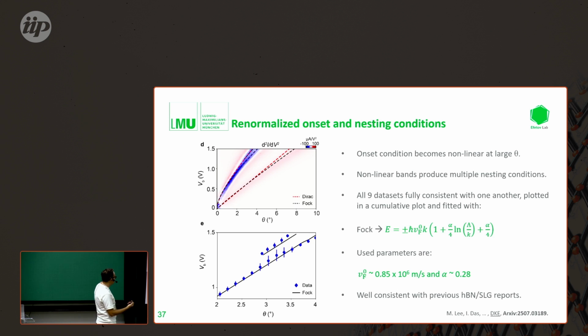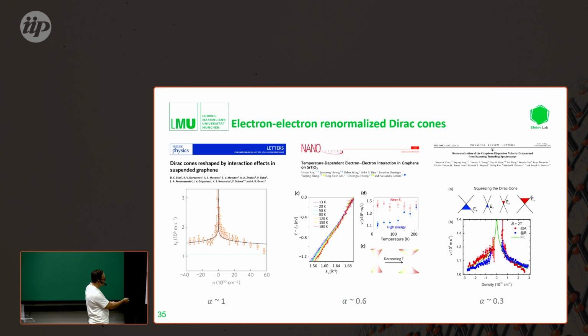The good thing about the QTM, which I found while doing this measurement, is that we can repeat this measurement 10 times on the same device, in different locations, for different tips and for different samples. We can bin these measurements from 10 data sets together and fit them. The fitting parameters we found from this binning are a Fermi velocity of 0.85, and alpha, which resembles the strength of the electron-electron interactions, of around 0.3. This is mostly comparable to the STM data, which was done in very similar devices.